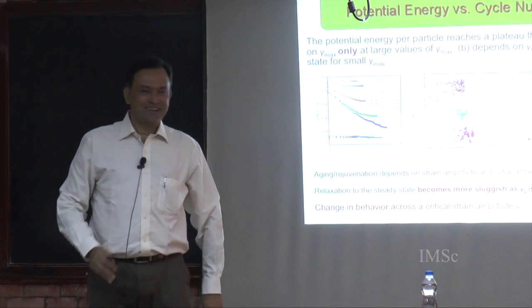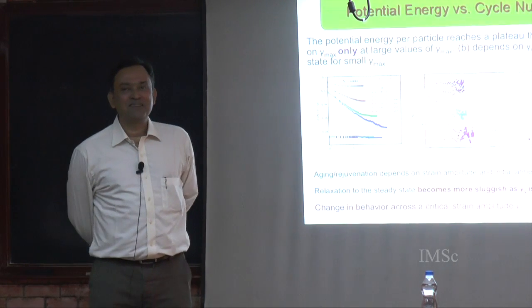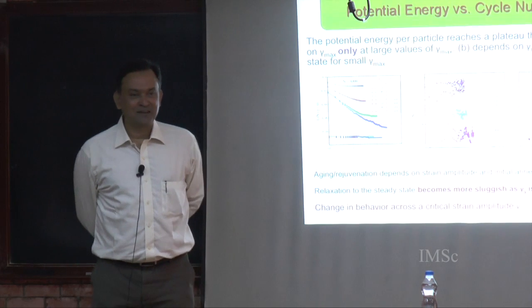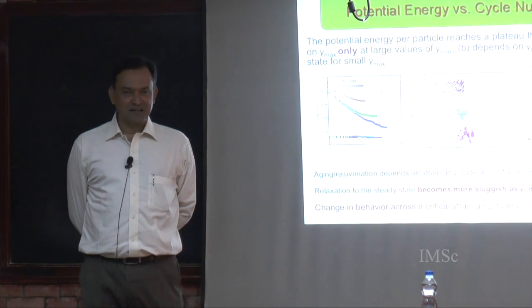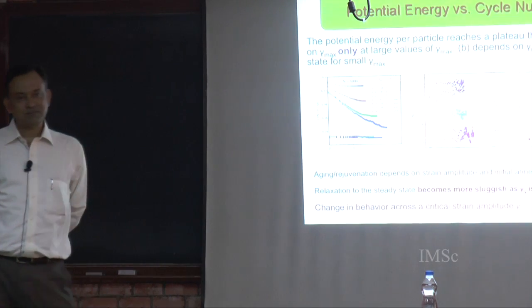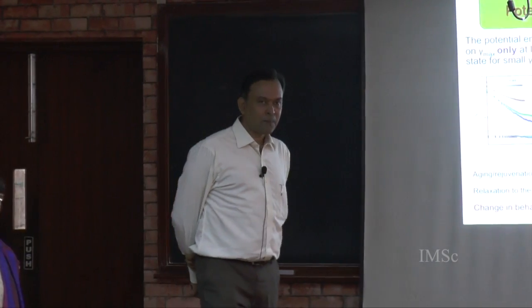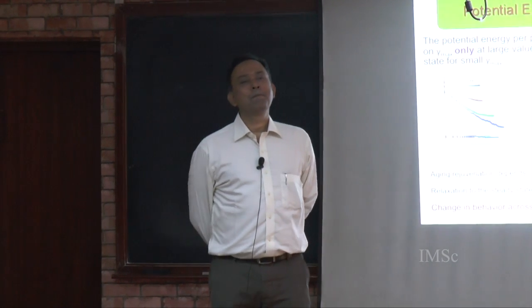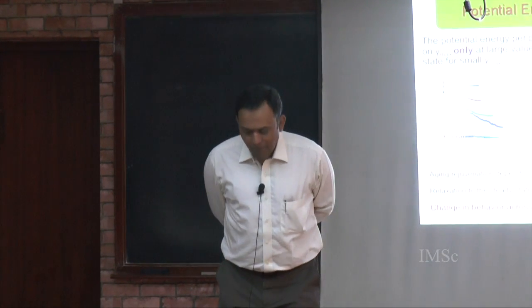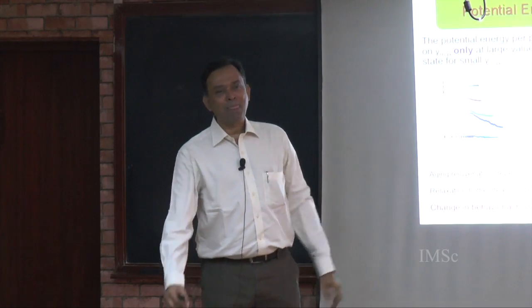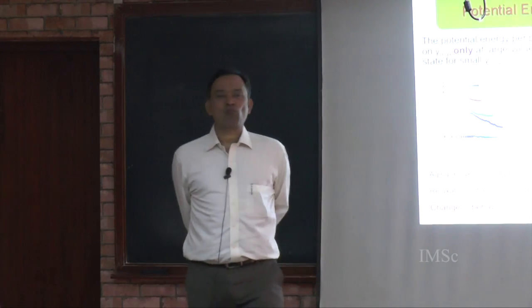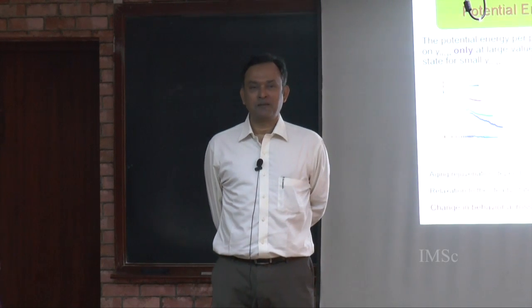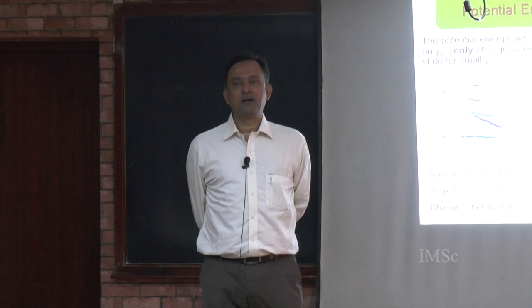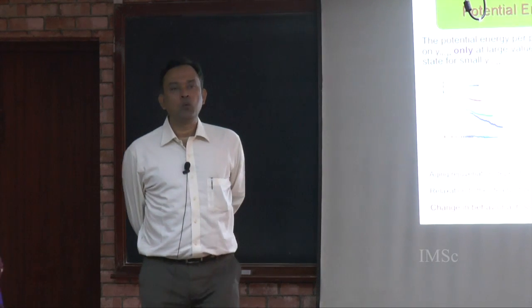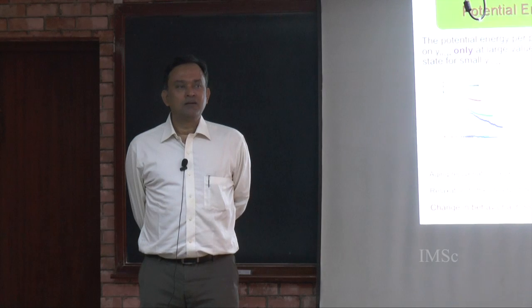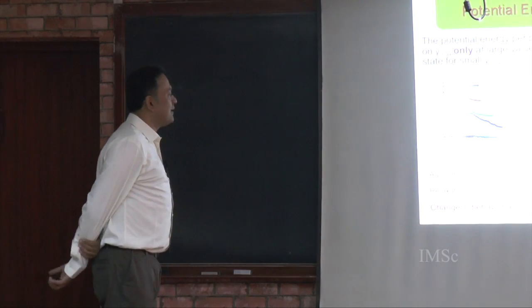So at the highest - okay, so the first part of what you said, it's not obvious to me in the sense why would there be dilatation. That's the Spaepen hypothesis in terms of the STZs, right? When you shear it, there is dilatation that happens, excess free volume is created, and that tends to widen the shear band. And then you also have structural relaxation, what you call annealing, simultaneously going on. Right, so these sort of balance each other, and then the shear band width saturates at some steady state level.